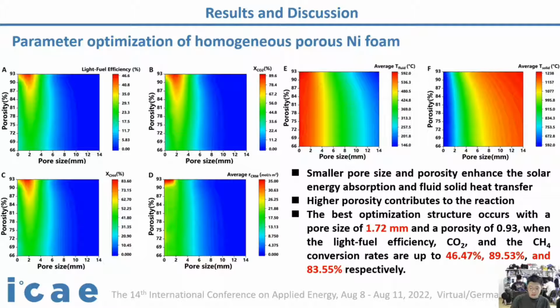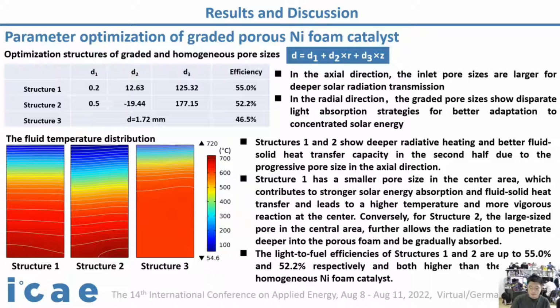When the light-fuel efficiency, CO2 and CH4 conversion rates are up to 46.47, 89.53 and 83.55% respectively. Then the optimization of graded porous nickel foam catalyst is carried out.